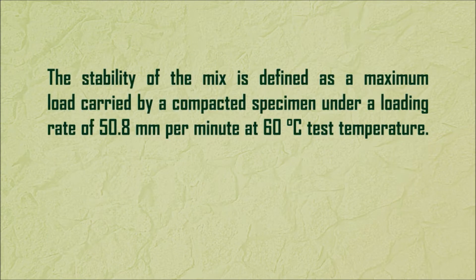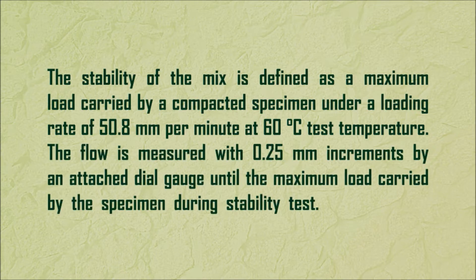The stability of the mix is defined as the maximum load carried by a compacted specimen under a loading rate of 50.8 mm per minute at 60 degrees Celsius test temperature. The flow is measured with 0.25 mm increments by an attached dial gauge until the maximum load carried by the specimen during the stability test.